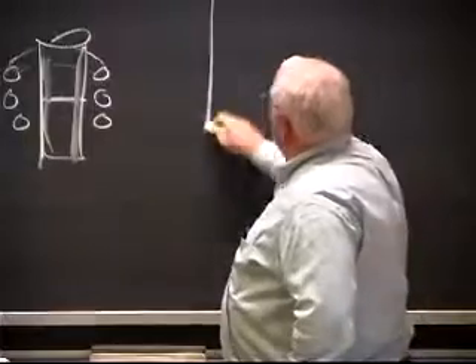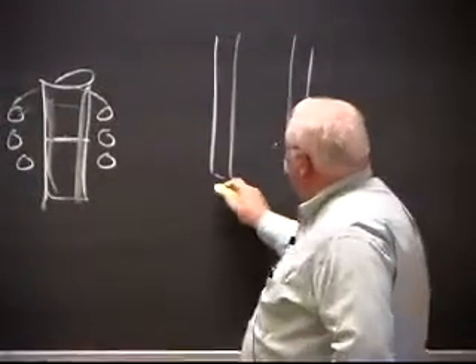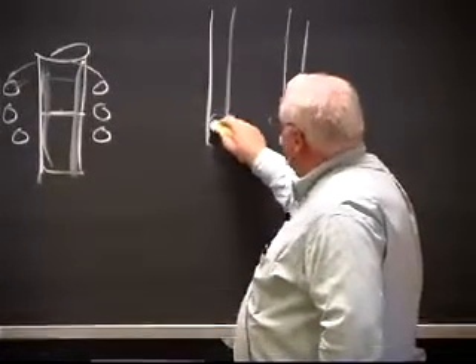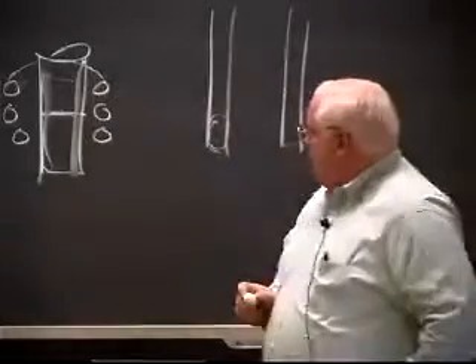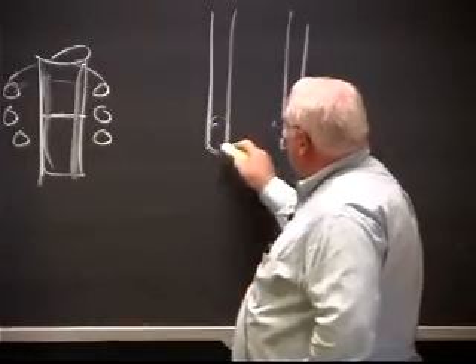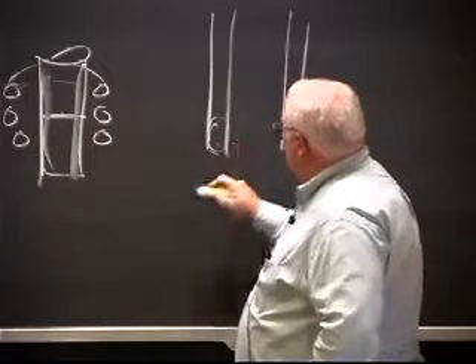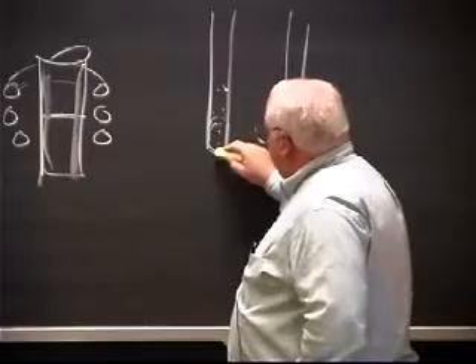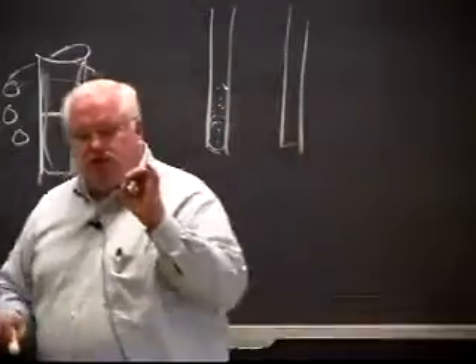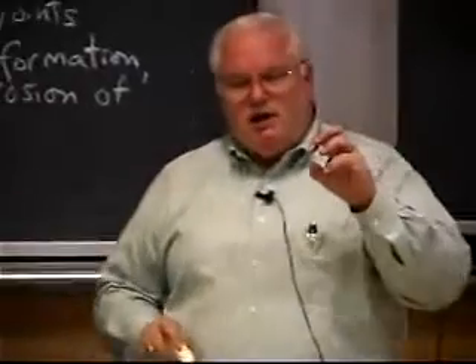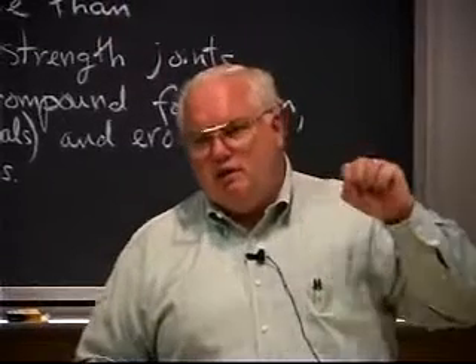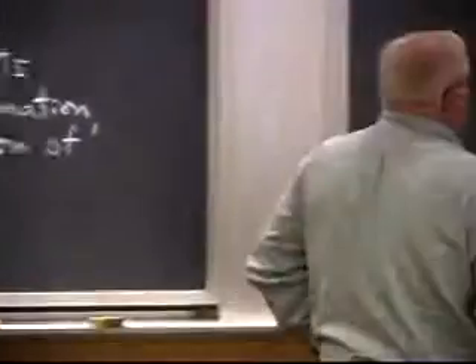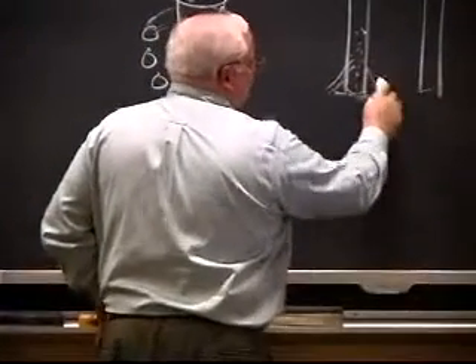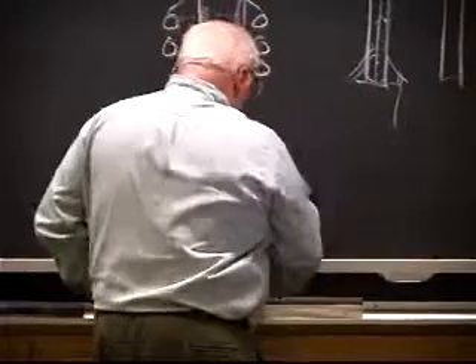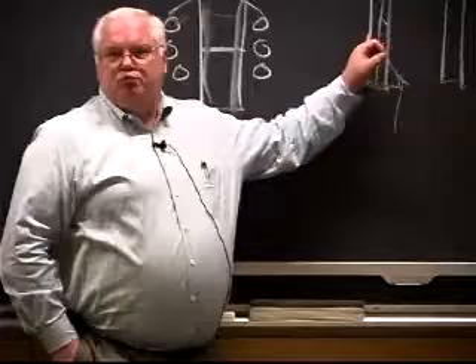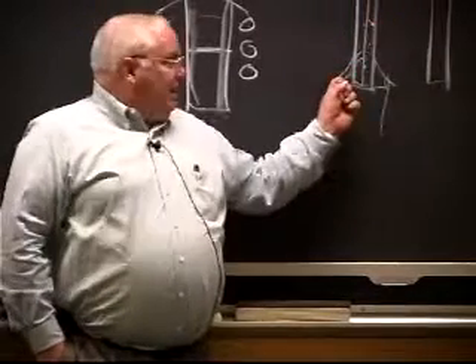Well, they wanted us to braze this tube, and it turns out that we ran into a problem. When we first tried to braze it, we found nickel alloys that would wet the carbon. Nickel likes to wet carbon pretty well and doesn't react with it to dissolve it. It's one of the few transition metals that doesn't dissolve carbon. But the problem was with all these little pores, the surface tension of each one of those little pores was acting like, or the liquid nickel was acting like the carbon was acting like a sponge to suck up all the liquid. And instead of just heating down here and forming our little seal that we wanted to form, nickel was going all the way up in, and we were wicking away all of the braze alloy. It was just being soaked up into the porous carbon like a sponge and leaving nothing for the joint.